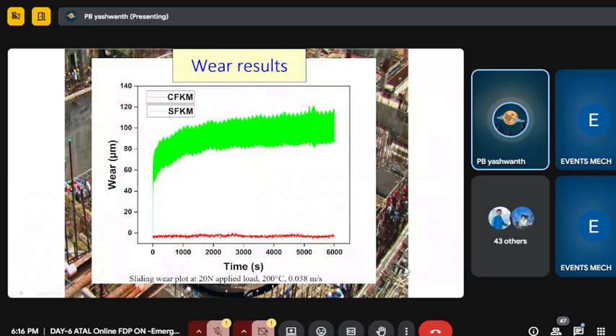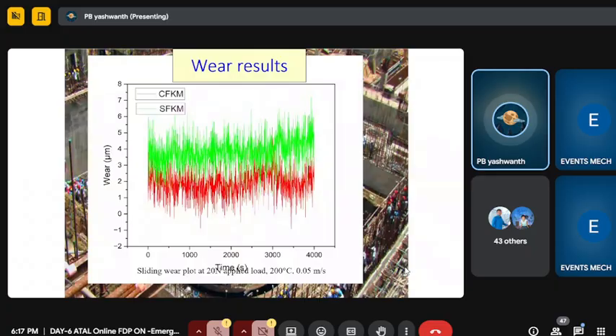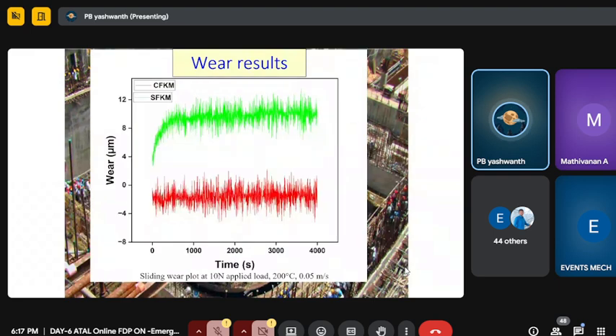Carbon based fluoroelastomer showed very little wear. You can see just a follow of zero and very, very minimal wear, whereas silicon, due to the marginally higher hardness, showed more pronounced wear. Coefficient of friction also correlated with the wear results. Silicon presented a higher coefficient of friction, carbon a marginally lesser coefficient of friction.